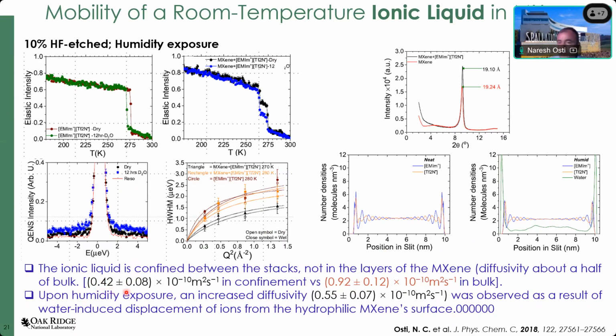Then we went to look into the XRD profile. We took the XRD profile of the pristine MXene and that of the ionic liquid confined MXene, where we found that the d-spacing, the peak position, is exactly in the same place. It means that in this system also, the ionic liquid is not in between the layers. It is between the interstack gap of the MXene that we have seen in our very first example of the